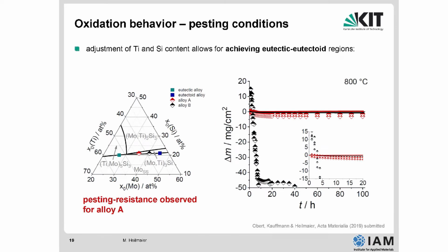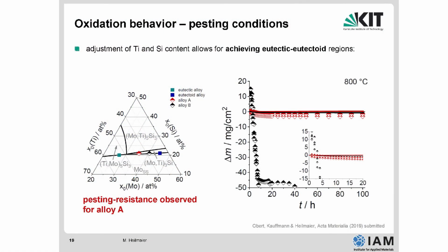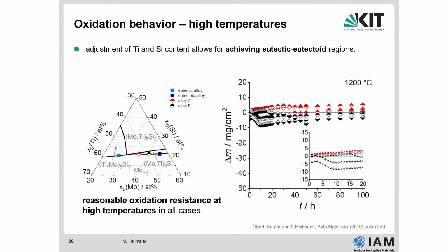Now let's look at the oxidation data again, because this is the initial proof. We want a non-pesting oxidation-resistant alloy. And to our surprise, we can afford some eutectic regions still. This alloy here, the alloy A, does not show pesting at 800 C. It still shows no weight change here, but the alloy with too much eutectoid areas in the microstructure does show pesting again. And this is the same behavior as previously shown for 1200 C. We do not see any noticeable weight changes. These are all small numbers here. So the material is quite oxidation resistant at the highest temperatures.